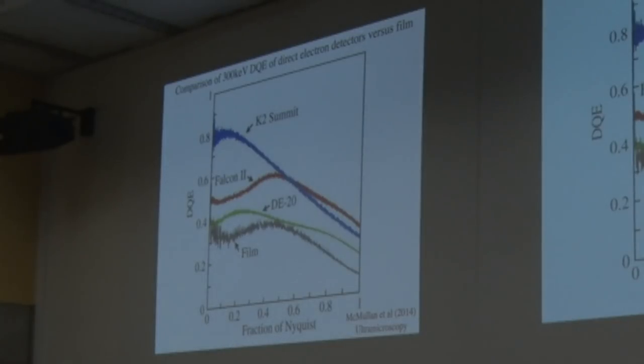And when we compared them then, this was the early measurement of detective quantum efficiency against resolution. This would be low resolution, this would be the highest resolution that you get with the pixel size that you've selected. Film was about 30%. And then these were the first three companies, Gatan, what is now Thermo Fisher, and Direct Electron. And they're all better than film.